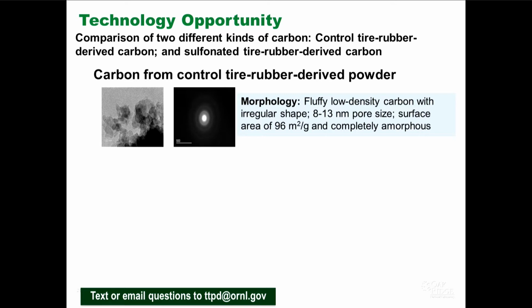So this is the control tire rubber derived powder. As you can see in the TEM image on the left, the morphology is fluffy, low density carbon with irregular shape. We have 8 to 13 nanometer pore size. The surface area is about 96 square meters per gram, and they are completely amorphous as per the selected area diffraction pattern you can see on the right.